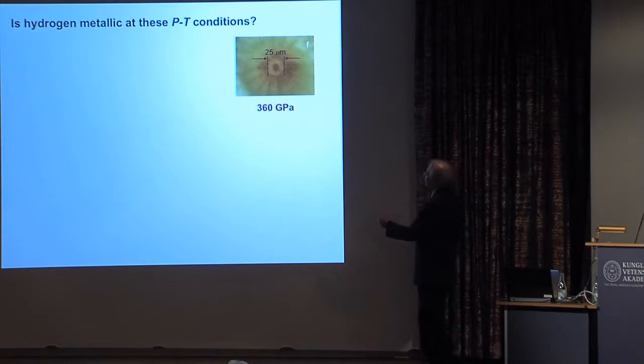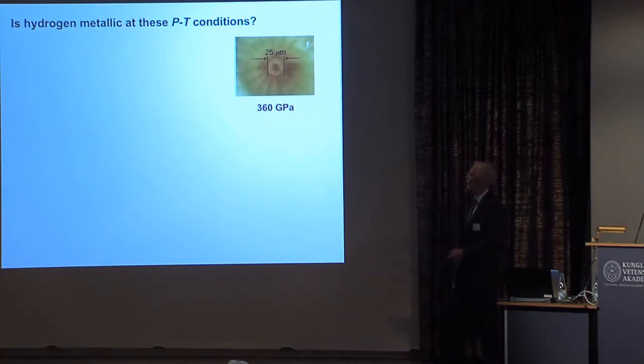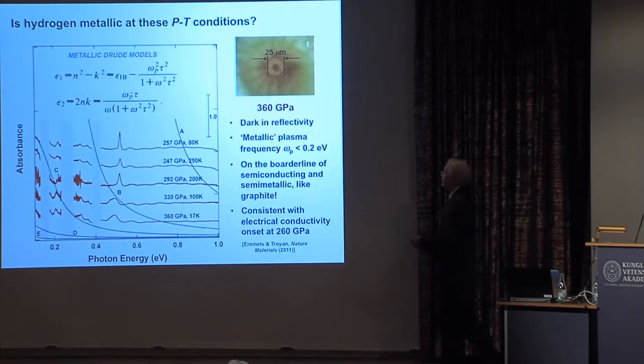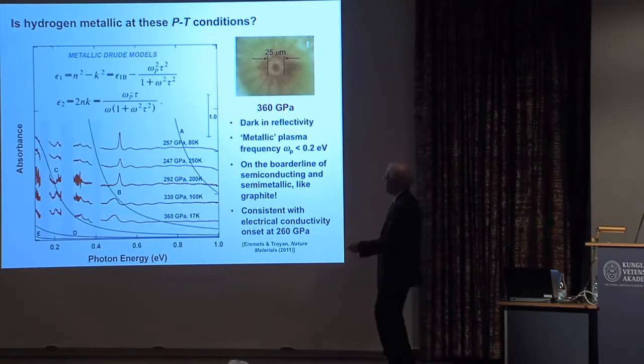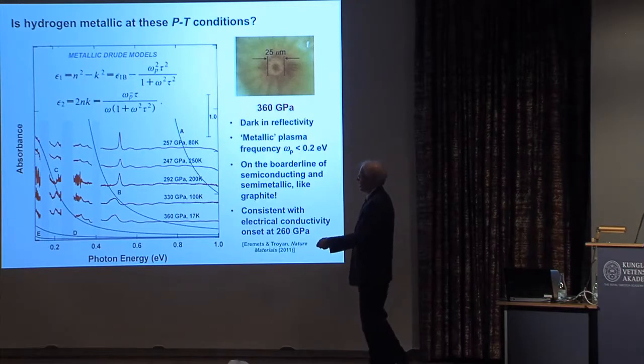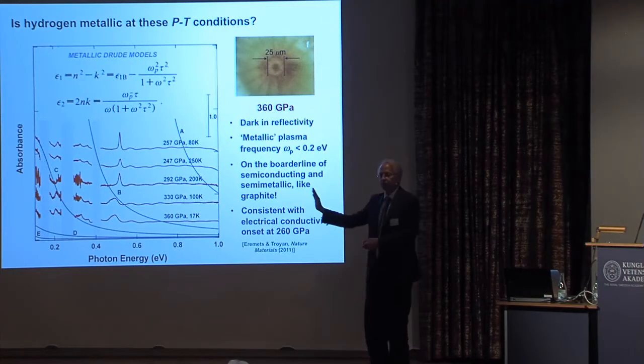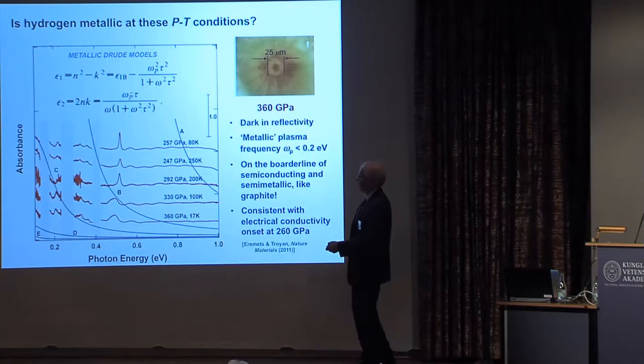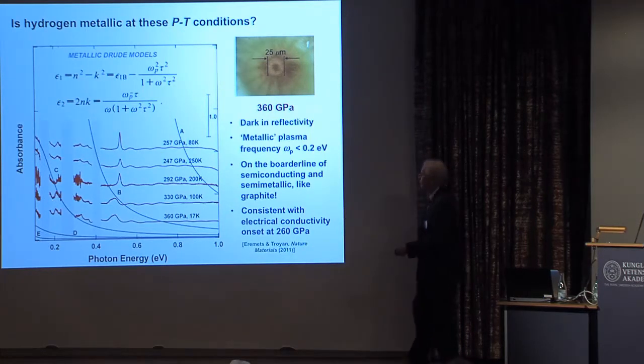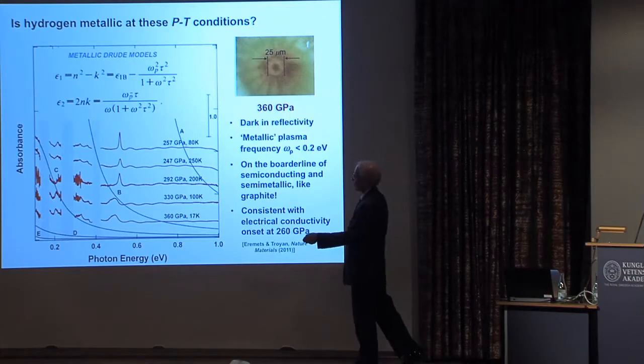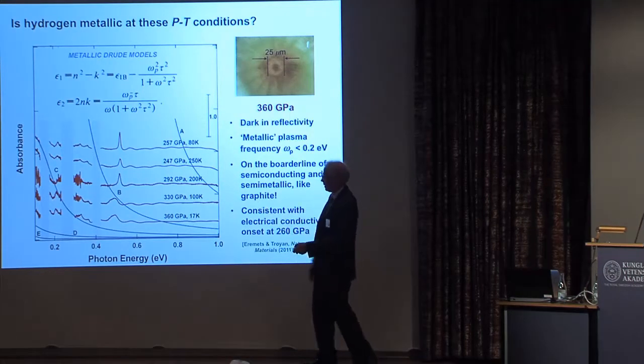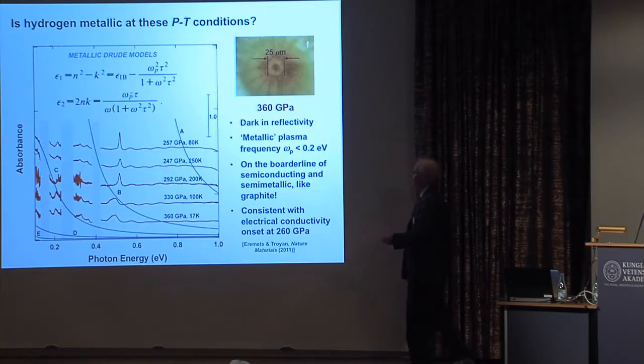Here's a photograph of a sample at 3.6 megabars, and you can see in reflected light that it's black. It's very dark in reflectivity. If one looks at the synchrotron infrared absorption spectrum out to the longest wavelengths that we can go, down to about a tenth of an electron volt, so this is mid-infrared, one sees basically a transparent sample, but there is evidence for a slight upturn in the absorption and the reflectivity.